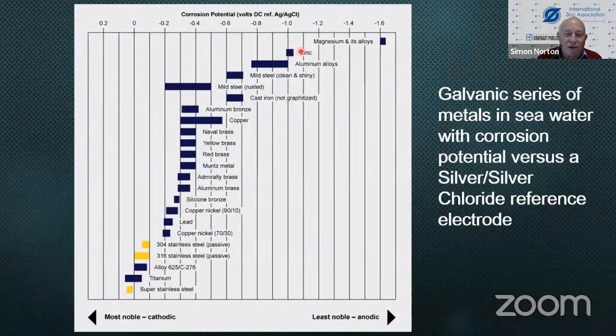If you look at this particular graphic, you will see at the top that this is a representation of voltages with respect to silver chloride. So what we do is we take a reference electrode, in this case a silver chloride electrode, which is silver in a silver chloride solution, and we measure the potential of zinc with respect to that reference point. There are others, but in this one we're referring to silver chloride. So you can see that zinc's sitting over here and mild steel is sitting over there. So there's quite a big difference in voltages between the two.